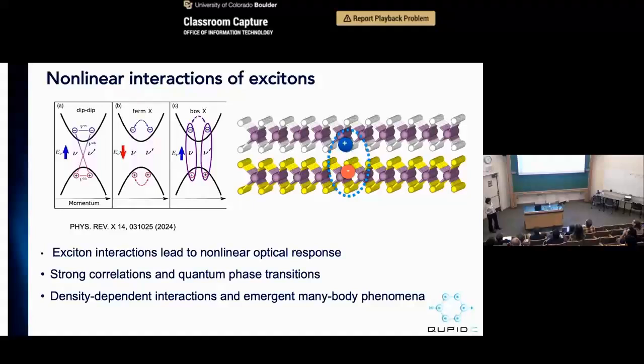And you can also have longer-range interaction. For example, the type of exciton that we are very interested in is called the interlayer exciton, where the electron and hole reside in two different layers of this 2D material, so that they have a permanent dipole. So you could also have these dipolar interactions that are much longer range. And these nonlinear interactions are very important because one of the hardest problems in physics is the many-body problem, right? If you can control this type of interaction, you could potentially study many-body problems by using them to simulate different types of phases.